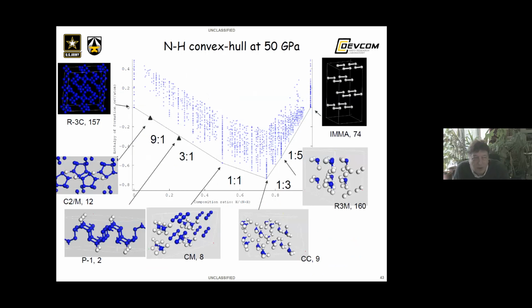Are the structures thermodynamically stable in terms of convex hull construction? Some of them are typical structures with ammonia, ammonium, and nitrogen and H2 molecules. Chain structures similar to that found experimentally for oligomers by Alexander Goncharov. In the variable concentration algorithm, one has much fewer generations and structures calculated than in the fixed concentration method. Particularly this structure for 9-to-1 concentration was missed in the variable concentration method. So this convex hull is a compilation of both approaches.